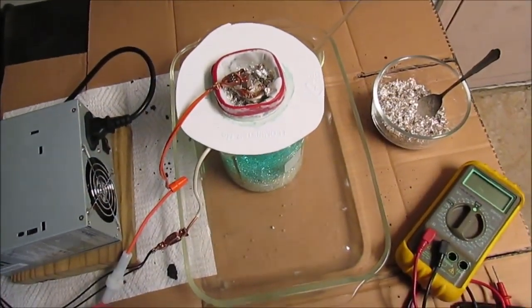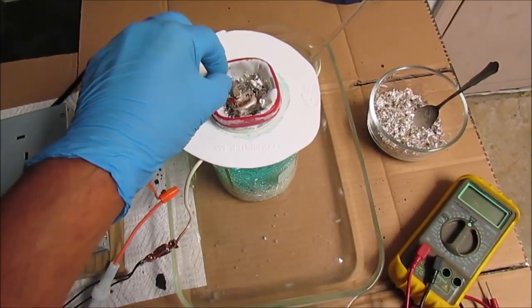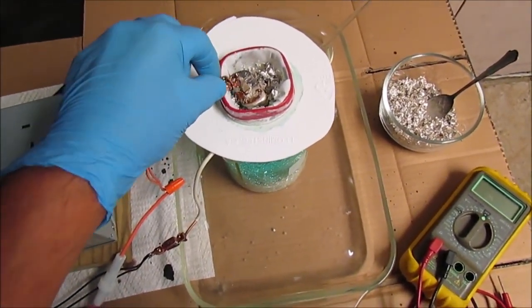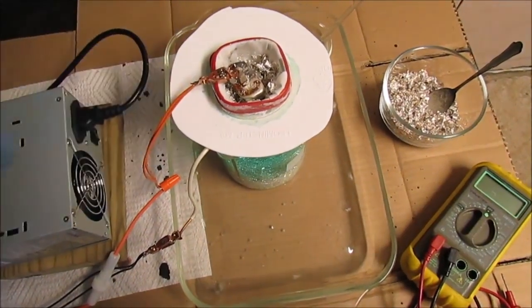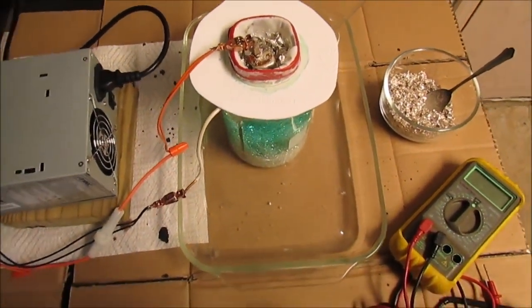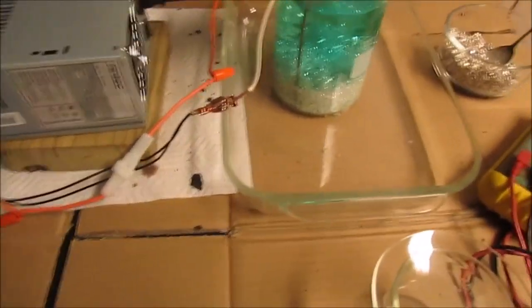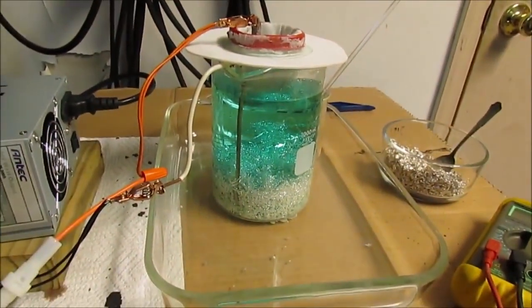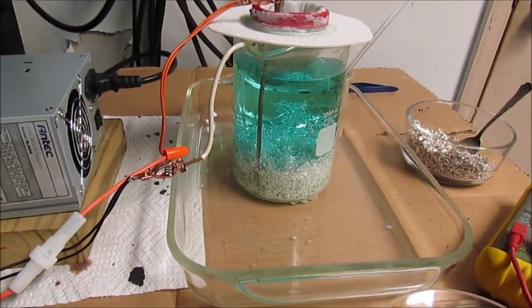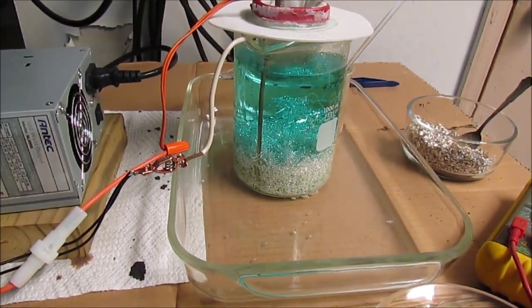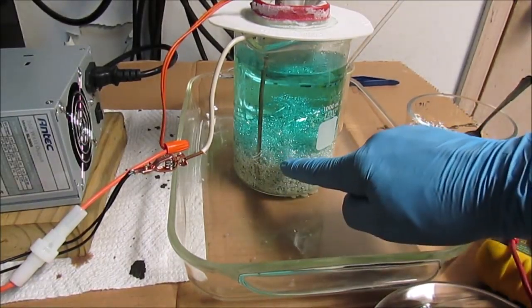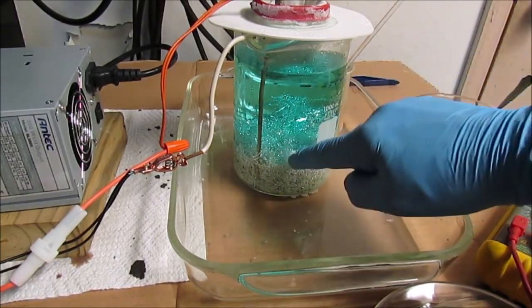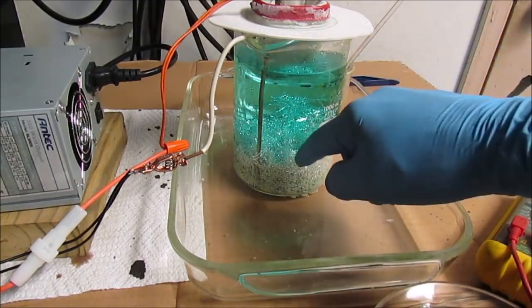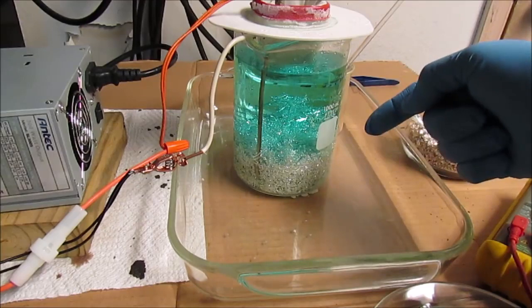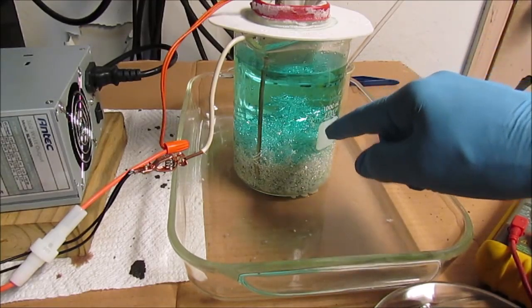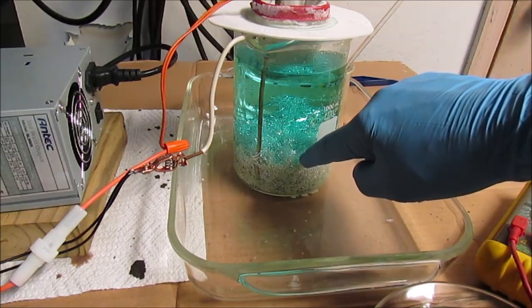This is day 5 of the silver cell operation. You can see in the anode filter here that most of the silver, it's down at least halfway there. So a lot of it's been consumed by the refining process. I've had this on now for about 30 minutes and the crystal level in here has gotten to the point where it's growing up and I'm having to come out here every 20-25 minutes to tamp it down. So I'm going to shut this down and harvest this crystal out of here.